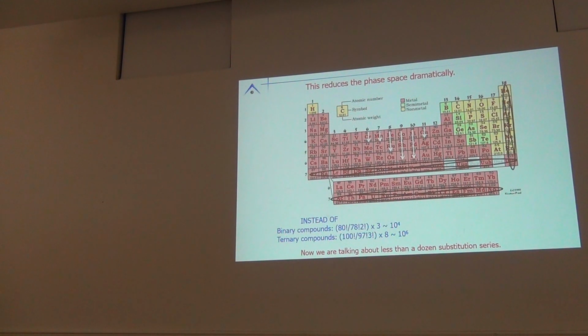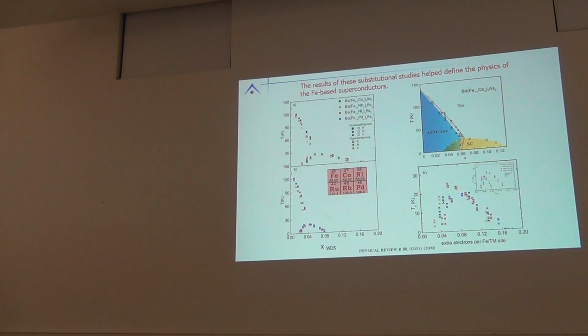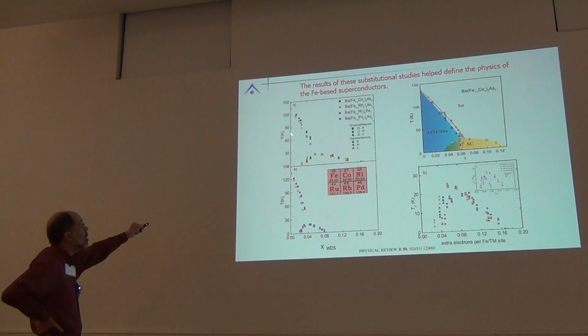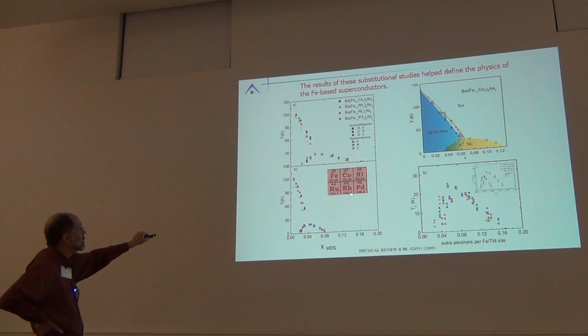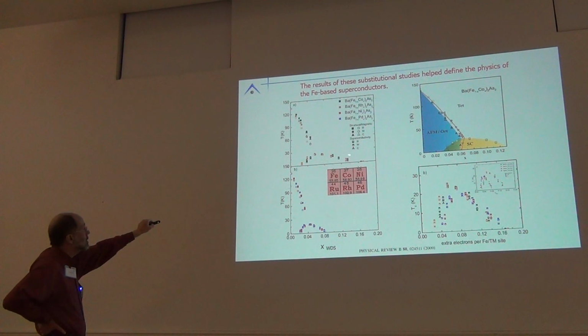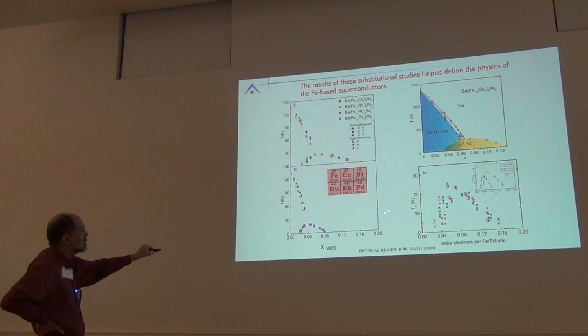Now, with these growths, which is what kept us busy in 2008, we could understand the rules just empirically, Edisonianly, of how superconductivity worked in these materials. What was remarkable to me is we could substitute in cobalt, rhodium, nickel, palladium, and for isoelectronics, so if I look at cobalt and rhodium, I have virtually the same phase diagram for how I suppress the antiferromagnetic orthorhombic, for how superconductivity turns on. If I look at nickel, palladium, the same phase diagram. Now, these two columns are not the same, but what's remarkable is if we look at the superconducting dome, it just scales with number of extra electrons.